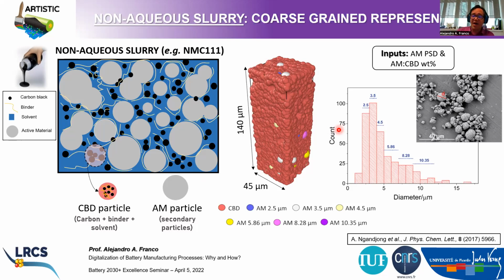So thanks to this simulation, we are going to be able to predict in 3D microstructures of slurries, right? And then the input of this model, this coarse grain molecular dynamics simulation using this coarse grain representation, will be the active material particle size distribution, that is something that we can extract from experiments, and of course the formulation, the weight percentage ratio between active material and CBD, right?